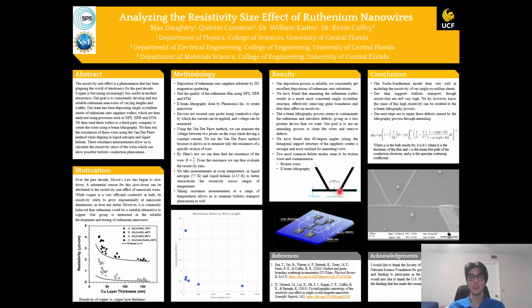And so the reason that we use this 4-probe technique is that if we were to use a classic 2-probe technique, we would be measuring the resistance of the wire, but we would also be measuring the resistance of the probe and the wires connecting the probe to the ohm meter, and we'd just be getting resistance that we don't actually want to measure. So we use this 4-probe technique instead. Once we measure this voltage, and we have this constant current, we can then calculate the resistance of this length of wire in between. And this is a schematic of the theoretical 4-probe technique.